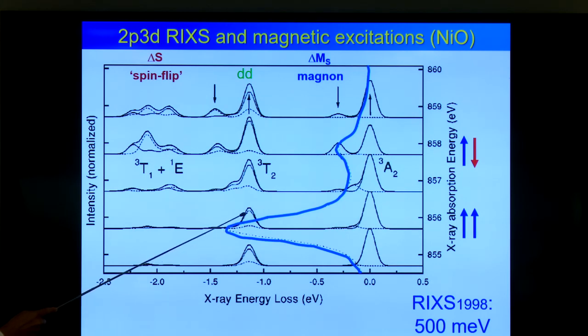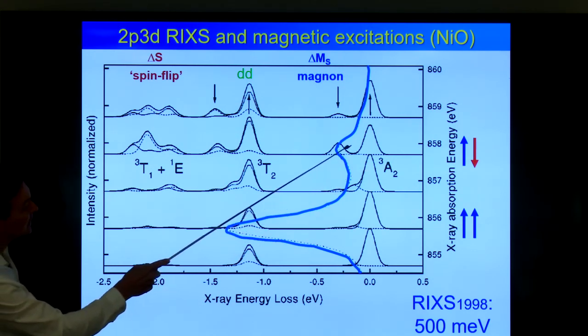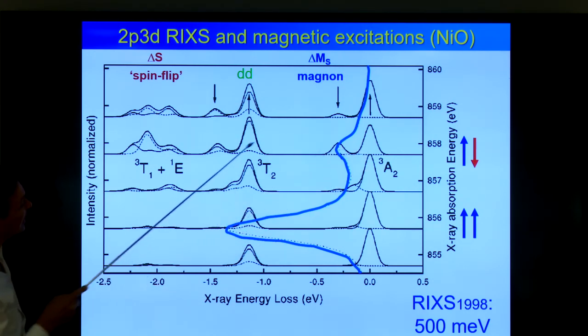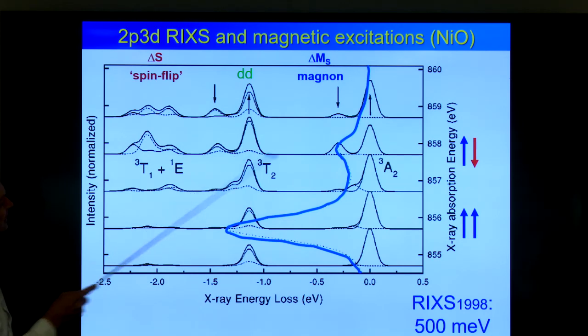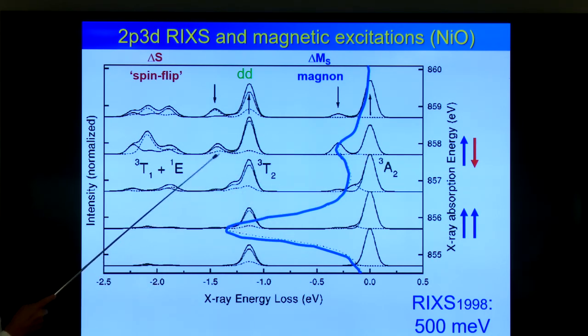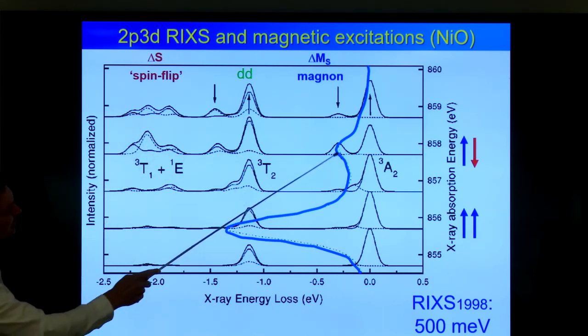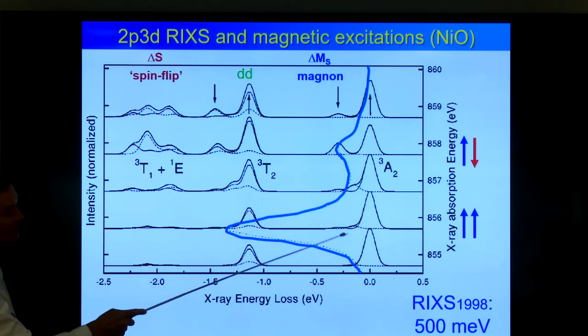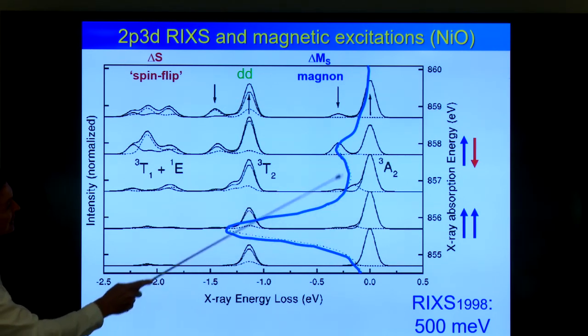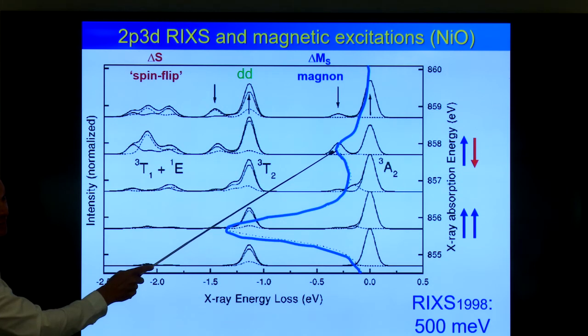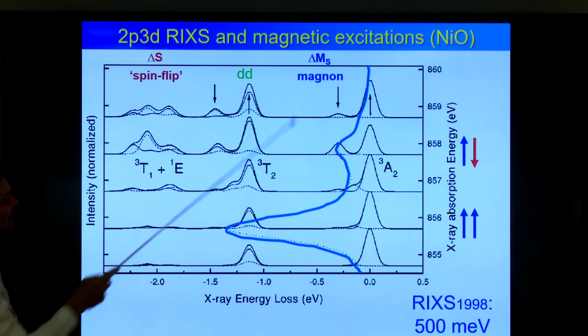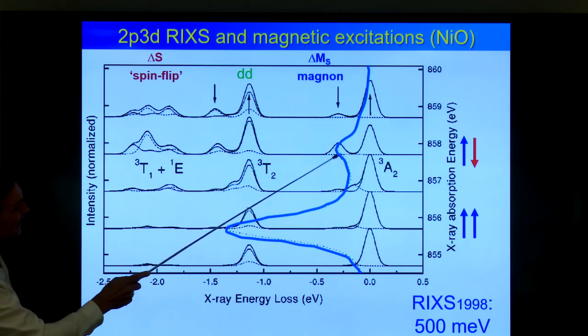So that was known, of course, also experimentally. So nothing very interesting. But if you excite at the satellite, you now see the DD transition, the elastic line, the DD transition, and here the other higher multiplet calculations, DD transitions. But you see a new peak at 250 millielectron volt, which is not visible there. And we call this the spin flip transition, or nowadays the magnon transition.